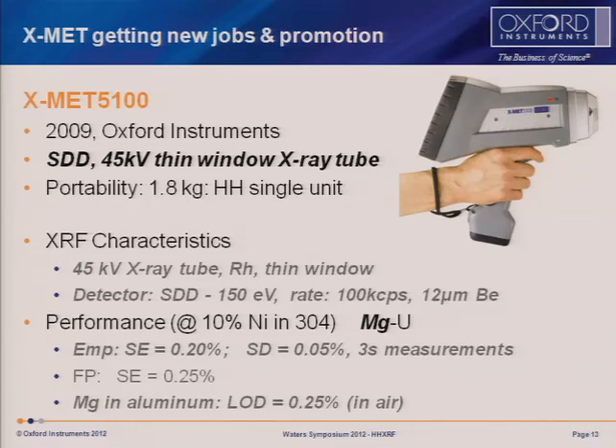It's an order of magnitude better than they were at the beginning of the X-MET's life. An order of magnitude improvement, it's just huge in terms of precision. It requires a 100-fold improvement, really, in counting error. Can now go down to magnesium, and limits of detection of magnesium in a very difficult spectrum in aluminum were achieved at 0.25%, but in air. The simplicity of the Finn's approach to it said, don't use helium, don't use vacuum, let's just do some neat optics and correct for barometric pressure. So perfectly capable of doing this in air. And in general, the time is again coming down quite nicely.